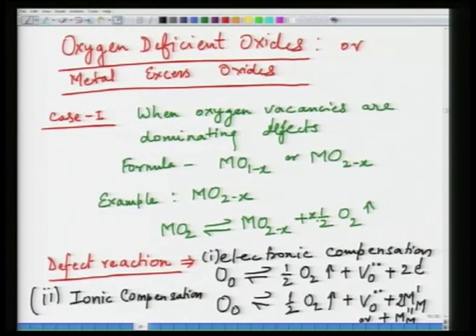And then we took various cases starting with oxygen deficient or metal excess oxides, and case 1 was where we took oxygen vacancies as the dominating defect, and we established how the defects can be formed. You can have electronic compensation of defects or you can have ionic compensation. Basically, in both of these cases you will have formation of oxygen vacancy coupled with either formation of quasi-free electrons, or reduction of metal on metal site.